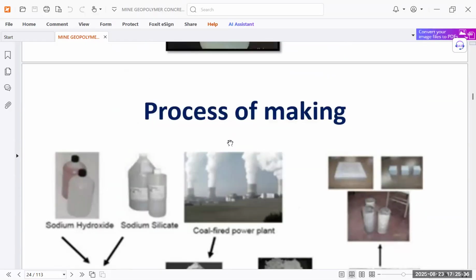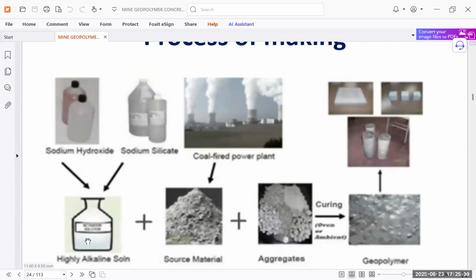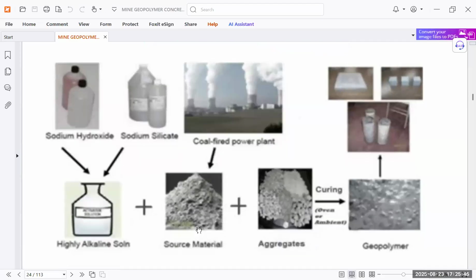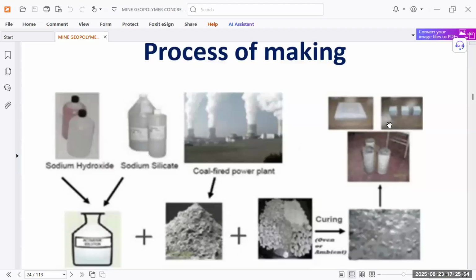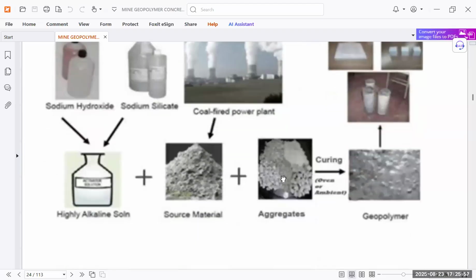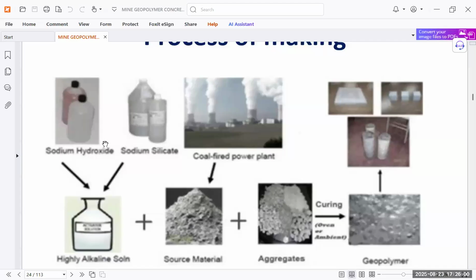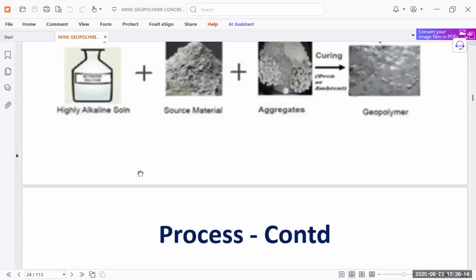So the process of making is: sodium hydroxide solution and sodium silicate are there, then we make a highly alkaline solution, and there is the coal-fired power plant. We use this waste here, and after that we use the aggregates as usual. Then curing is in oven or ambient temperature. Then geopolymer is made, and we use it in making of cubes, etc., whatever site work we have. You can see that we are not producing CO2 here, because cement is not there, and water is also not needed. That means cement CO2 production is reduced, and water use is also less in this case. That is why the requirement of the time is met using this.